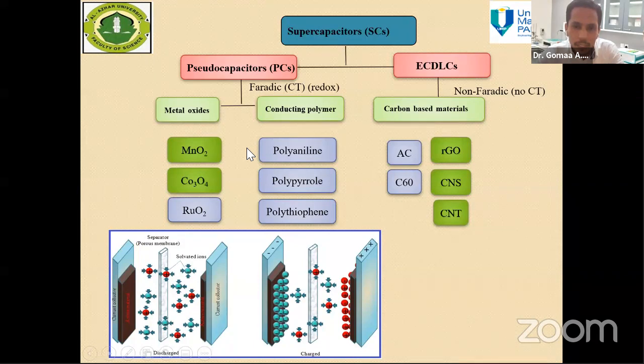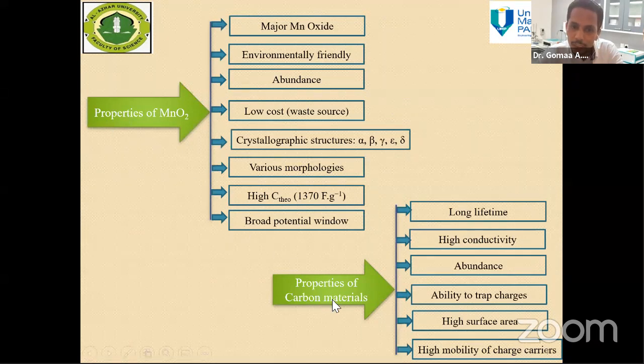So most popular candidates for supercapacitor electrode materials are manganese oxide and carbon materials. Why manganese oxide? Because it has a lot of advantages which recommend it as a suitable candidate for supercapacitor applications. It is environmentally friendly, abundant, low cost, has different crystallographic structures, various morphologies, including nanoflower and nanorod, as we can see from the scanning electron microscope image later on. It has a high theoretical capacitance of around 1,370 farad per gram, and a broad potential window. It could work under a wide potential range of the applied voltage.